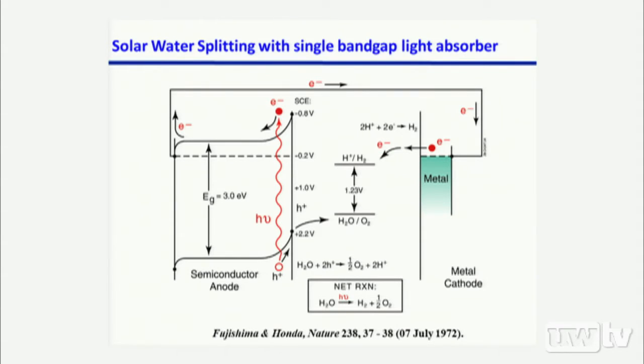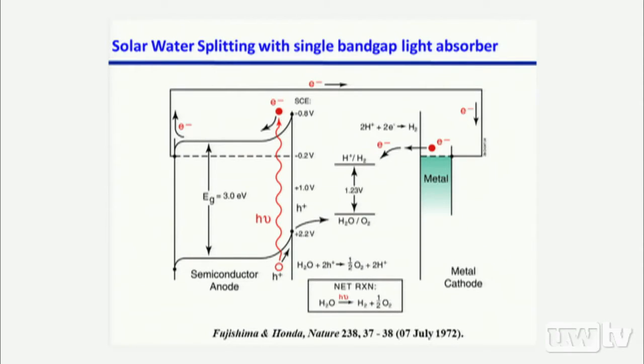So if we look at the water reduction and the water oxidation, the minimum energy you need to drive those two half reactions is 1.23 volts. Then for any of these half reactions, you have overpotential. So essentially, in terms of photovoltage from the semiconductor end, you need more. It typically would be more than 1.5 volts. So TiO2, as a UV material, will give you enough photovoltage to drive those reactions. Unfortunately, if you are using TiO2, you are only utilizing UV photons. And if you are using only UV photons within the solar spectrum, then your ultimate energy conversion efficiency would be quite limited. So this is not going to eventually be a viable technology.